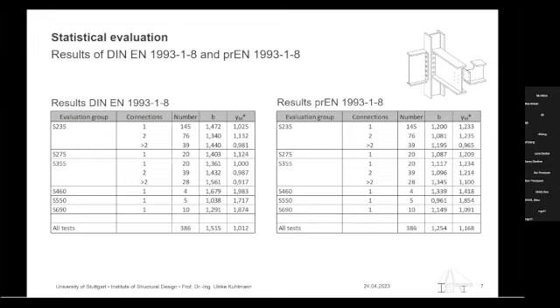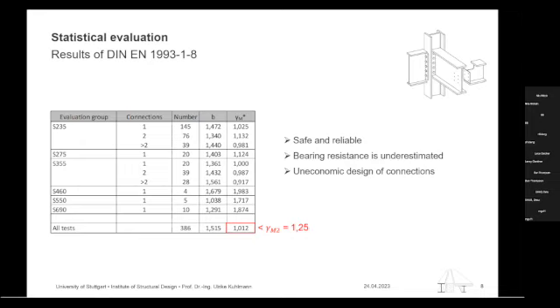On the right side now, additionally, are the results of the design concept according to the draft prEN 1993-1-8. I don't want to discuss all of these numbers, but want to show you the partial safety factor of all tests and compare them, because the partial safety factor of the draft is higher than the one from the DIN, and it's also closer to the gamma M2 factor. So we can sum up that the DIN 1993-1-8 is safe and reliable because it's smaller than the gamma M2, but the bearing resistance is underestimated, which leads to uneconomic design of connections. And now we can say that the DIN 1993-1-8 leads to conservative results.